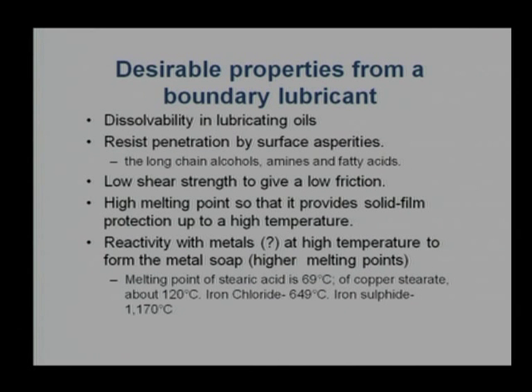That means this can sustain above 500 degree centigrade temperature without failure. However, if you want to go further on the higher side, then sulfur should act. Obviously, the iron sulfide, which will melt at 1170 degree centigrade, gives a very high temperature. They can be used as high temperature additives. They are giving good results at the high temperature.